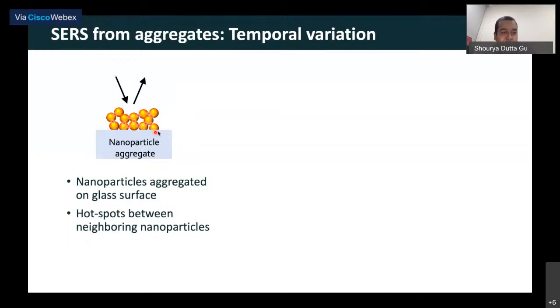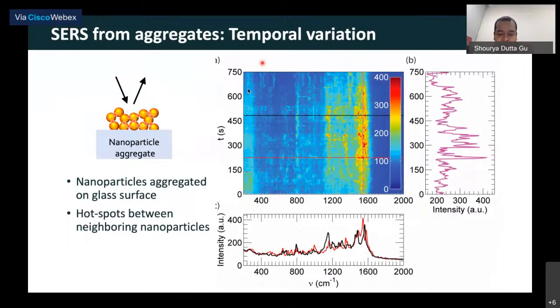So for this structure, if you send light from the top, the laser from the top, and look at the reflection, what we get is shown in this plot here. So the color map here, the horizontal axis is the wave number or the Raman shift, and the vertical axis is the time. Now Raman, we know very well that it always fluctuates because the molecules are in water and the molecules keep moving, right? So if I take two different times, like the red curve and the black curve, and look at the cut that is shown at the bottom here, I see nice peaks which correspond to the Raman peaks from the molecules that are there in the sample, but they vary significantly. So the red one is very different from the black one.